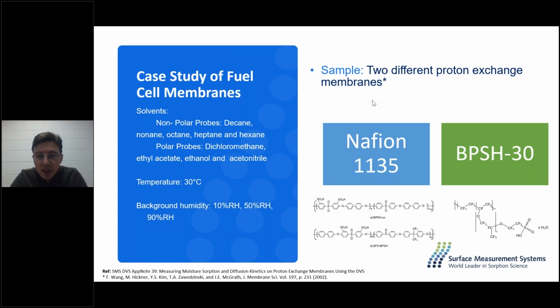So here we can see the different materials that we'd like to look at. And we were looking at not only the dispersive surface energy, but the specific surface energy. And here we can see the probes that we used. So we packed a certain amount of these membranes into our column. We put this column at 30 degrees C throughout the experiment. We did a number of controlled injections of our probes.